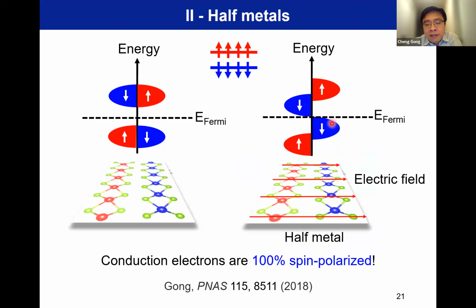The second part of the question is about whether they will hybridize. Yes, as you can see simply from the band structure like this, we did not consider that part because it's just a Van der Waals gap. Of course, there is wave function overlap. In practical devices, the electron may easily hop between layers. But the key is that close to the Fermi level, no matter whether in this layer or this layer, you have the same spin. Even if this one gets excited to here, it's still the same spin. We are okay if there is a certain probability of interlayer hopping, as long as it's not depolarized.